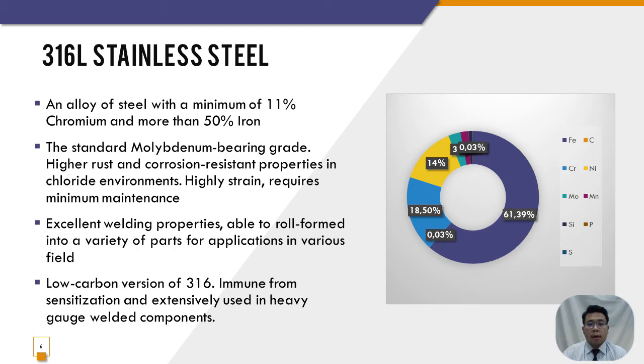The chromium carbides tend to precipitate at the grain boundaries of any austenitic stainless steel in the 400 to 700 degrees Celsius temperature range, which usually occurs during welding or hot forming processes. Any exposure or thermal excursion into this temperature range could potentially sensitize the steel, which is why the 316L grade is more extensively used in heavy gauge welded components.